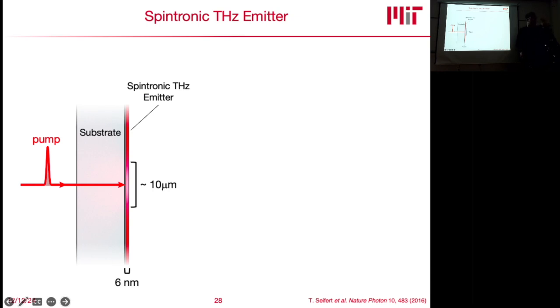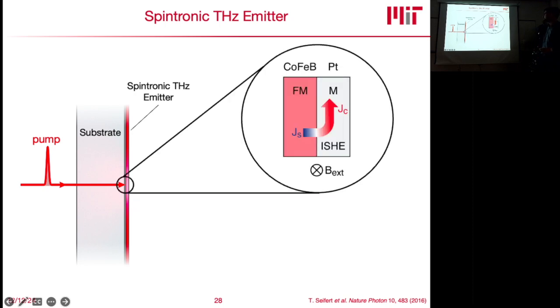These are incredibly small metallic sandwich layers of a ferromagnetic metal and a heavy metal like platinum on top of a common substrate. And these layers are 6 nanometers thick. They're incredibly thin. And if you excite these terahertz spintronic emitters locally with the pump pulse, in this case a near-infrared laser beam, you will launch a superdiffusive spin current in these materials.